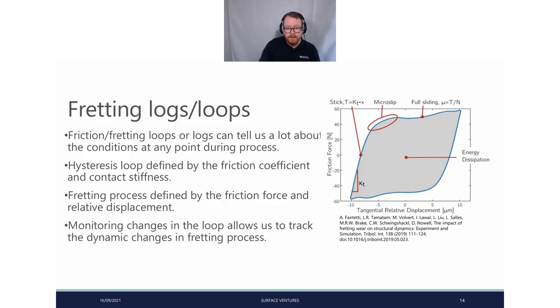It can tell us a lot about the conditions of your fretting process. One of the things you want to do is make sure that whatever type of equipment you're using, you're able to measure this as you go. It can tell you a lot. So this hysteresis loop, this closed loop, essentially we're expending energy into the fretting contact. So it's defined by our friction coefficient, which essentially gives us the height of our log, and the contact stiffness, which gives us how steep it is. The higher the contact stiffness, the steeper our loop is, the lower the contact stiffness typically. Then this can change.